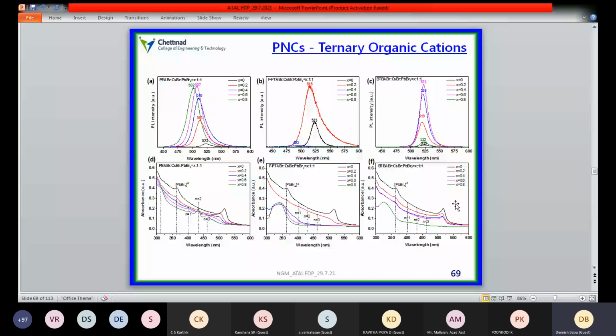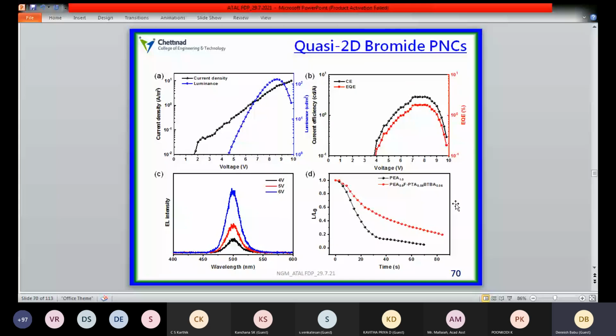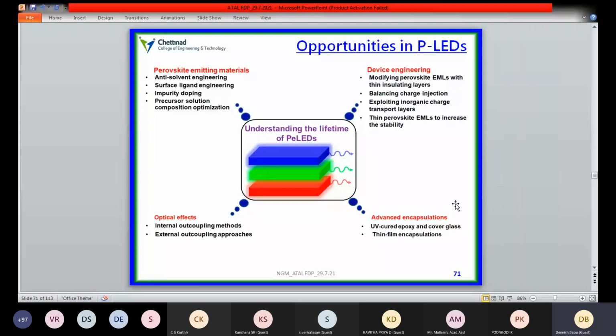And these are their optoelectronic characterizations: the voltage versus current density curve, luminance, and current efficiency with respect to the external quantum efficiency of the perovskite devices made from quasi two-dimensional cesium lead bromide systems. So for those working in the field of perovskite LEDs, a variety of different opportunities are available.